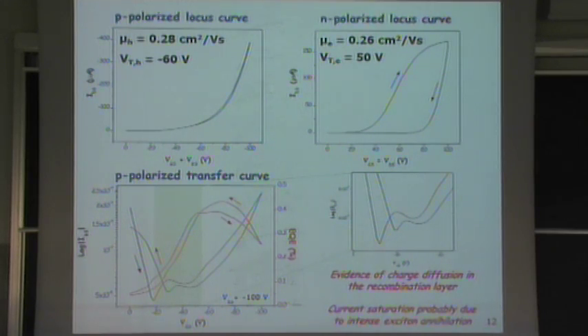It's important to note here that we have evidence of charge diffusion in the recombination layer. You can see from here, because there is a hysteresis, and also here, there is a little bit of saturation at more or less minus 30 volts. But you see the current goes down, but the light goes up. So it's a proof of migration of electrons into the recombination layer.